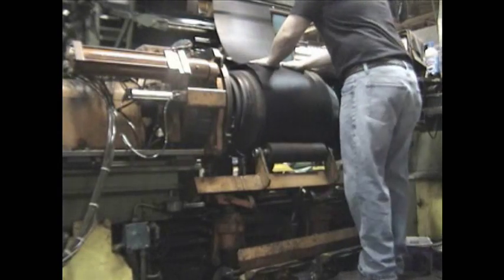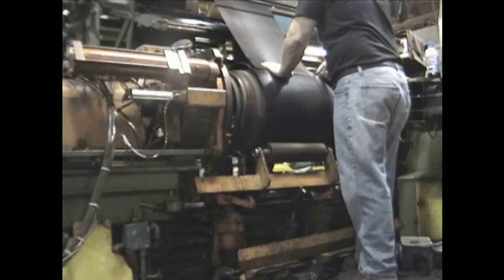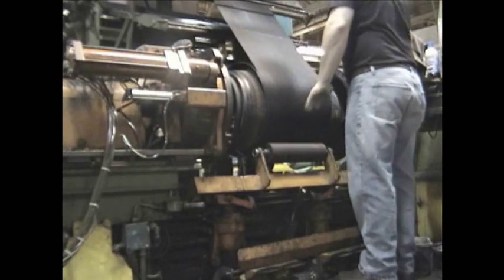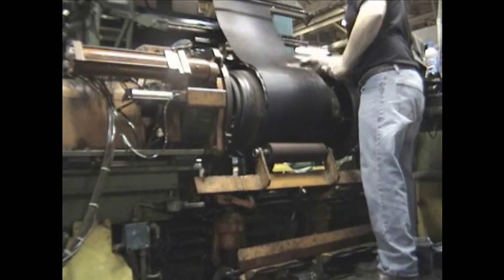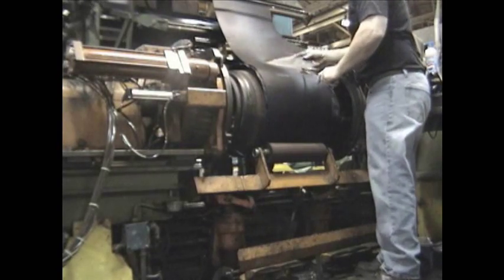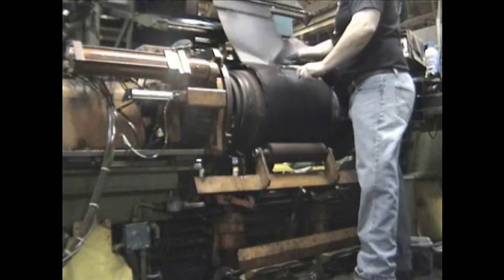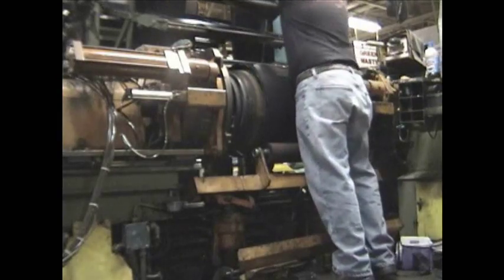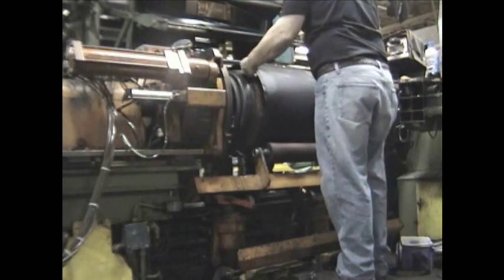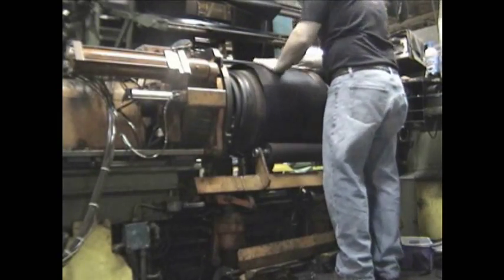This is the second ply. Put the second ply down. Hit the foot pedal. Rotates another 180 to 360 degrees for this ply. Trim. Cut with maybe an eighth inch to maybe three sixteenths overlap on the ply. Make sure it's lined up. Hit the foot pedal.